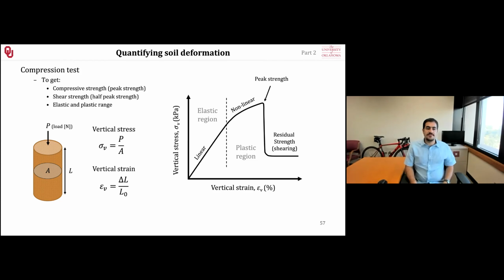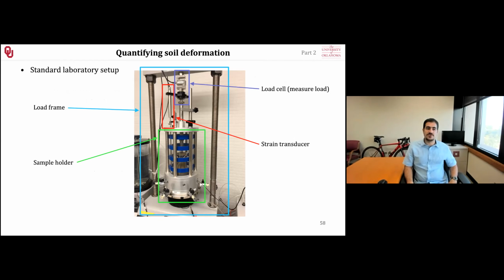We will do that in the lab with an instrument called a triaxial instrument. Usually we have a load frame that will apply a very small stress on the sample over time and basically push it so it compresses. We will measure the changes in length with a strain transducer. We will measure the amount of stress with a load cell. And if we want to do a triaxial measurement, we need confining stress as well. We can fill up the sample holder with water and measure that as well. Well, in here, we didn't use that.